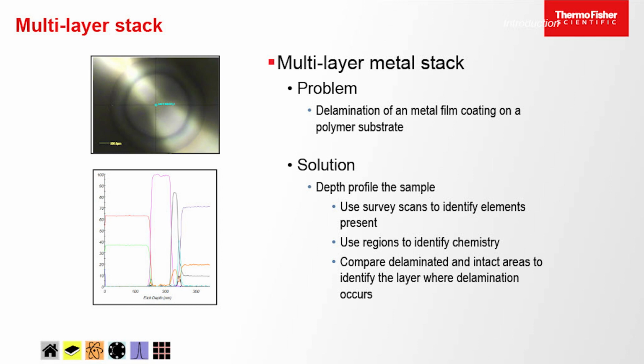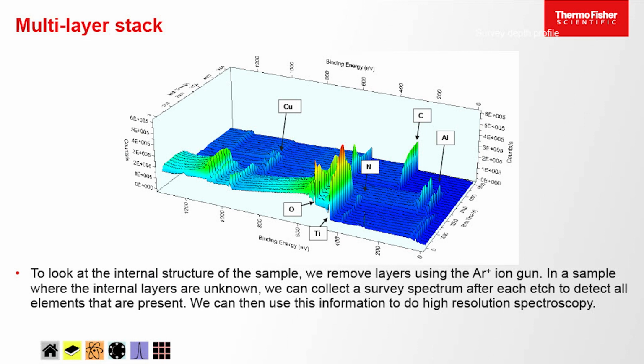So there's quite a lot of technology involved in preparing this sample, which is interesting because the actual material itself is pretty cheap and everyday. It's gift wrap for parcels and things like that. It's that sort of metallic, shiny stuff that you might wrap things in for Christmas or birthdays. And it's delaminating a little bit. So what we want to do is look at the layers and try to establish where it's breaking down. To do that, we've got to understand what the layers are, because we don't know exactly what elements we have present. So this is a 3D plot of depth profiling, where we're etching into the sample, so the etch time is along this axis.